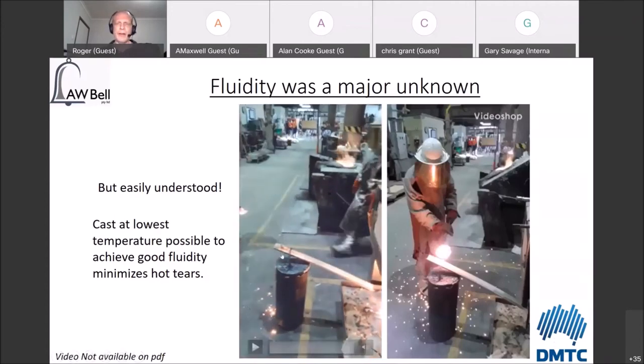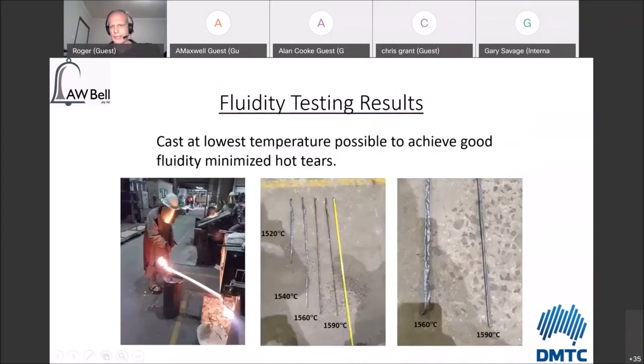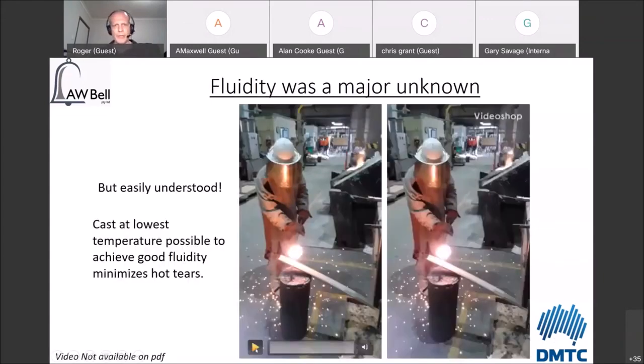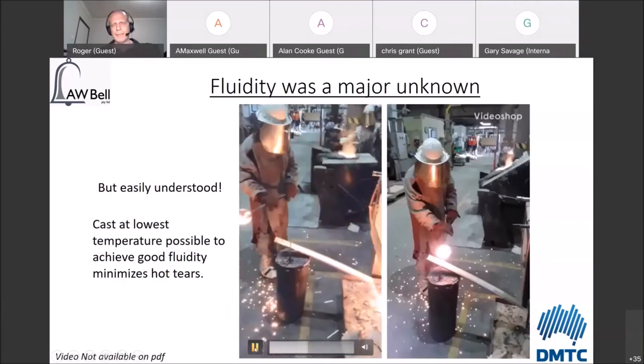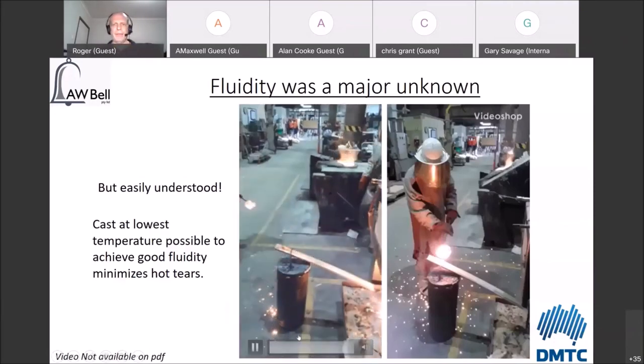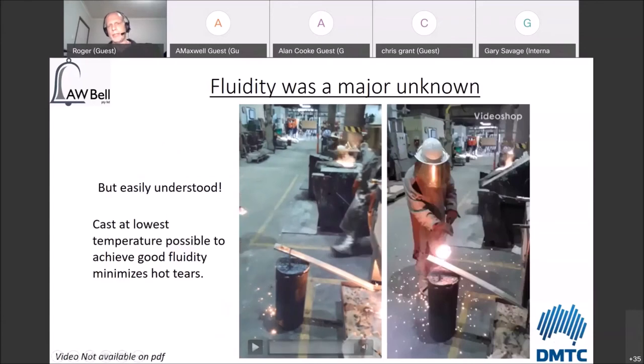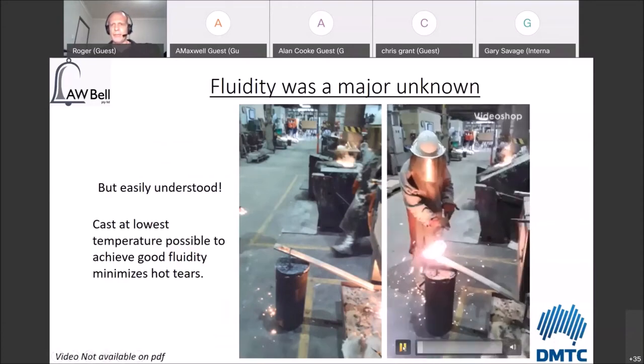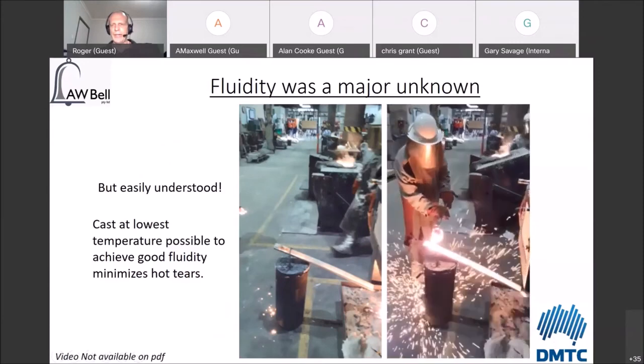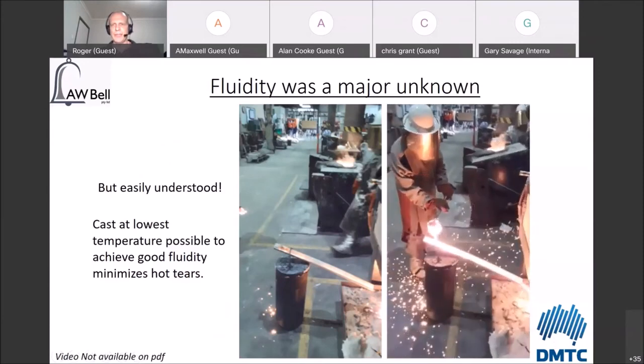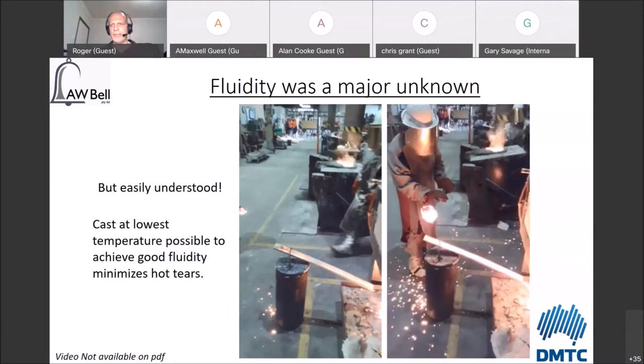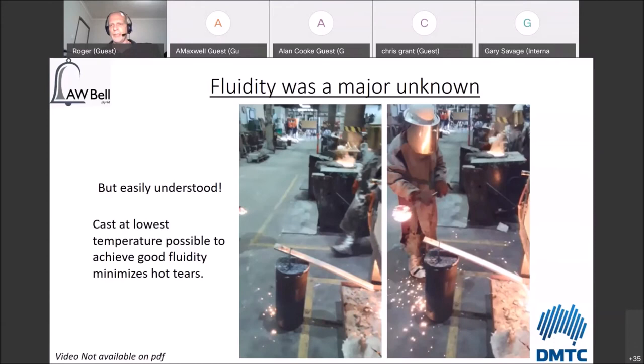Okay, so that's about 5 seconds in that one it took to run down there. Now just run it again. You need to watch the metal as it's running down, and it's very, very fast the way it goes down the angle. Now, if I take that to about 1/3 the speed, so you slow it right down, you get a completely different view of what it's doing. And you also get a feel for how fast it's actually traveling. Basically, it's moving incredibly quickly under these conditions.